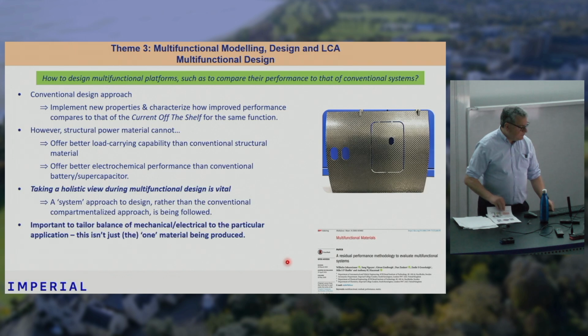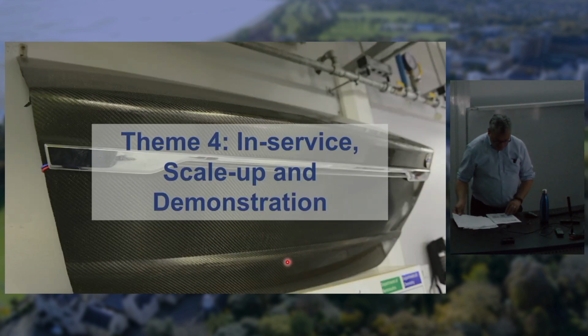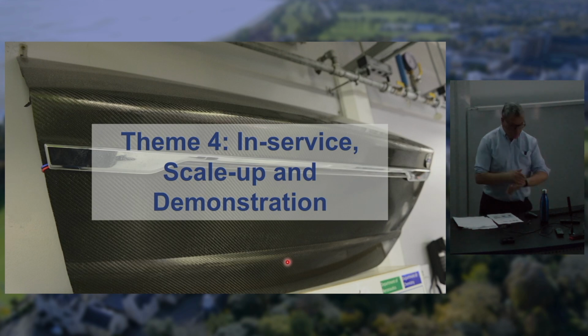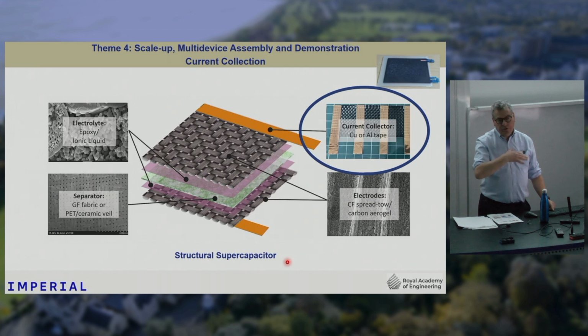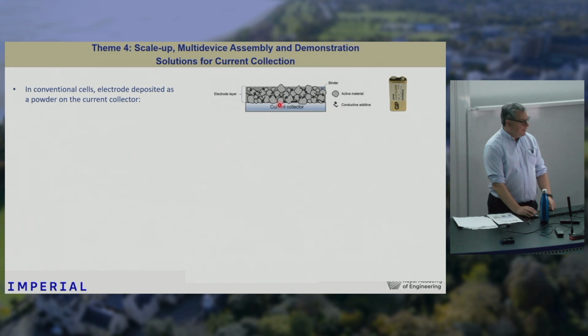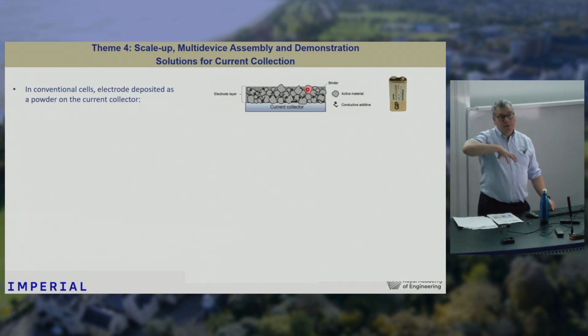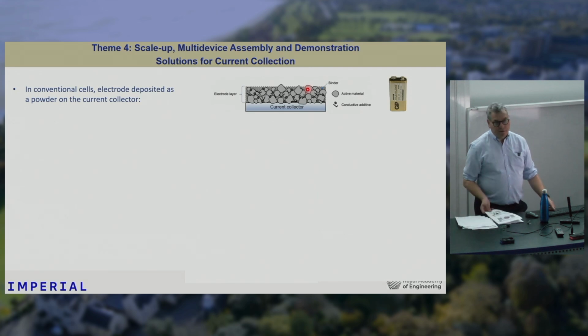Let me skip on to the sort of final theme, which is focused on some of the sort of scale-up issues associated with this technology. So current collection is something that I've touched on before, and this is quite a difficulty for us because with the supercapacitors, everything is driven by how quickly you can deliver the energy. And with conventional devices, we have a current collector, which is a metal film, and the electrode is then added to that as a powder, and there's a binder there that holds it together. But it's the current collector that actually supports as a scaffold for the active material. So the current collectors actually turn out to be quite heavy. They can account for about 25% of the mass of your conventional supercapacitor.